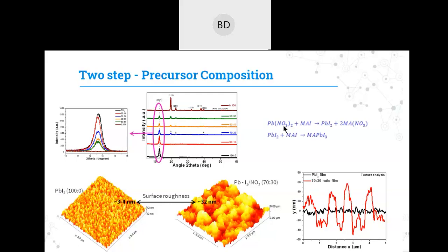What is this lead nitrate doing to change this kind of morphology? Generally, if you use lead nitrate with MAI, it doesn't directly convert into MAPbI3. It also goes through an intermediate phase change. First, if you use lead nitrate with MAI, it forms PbI2, and then that PbI2 with MAI forms the MAPbI3. So this is again an exchange reaction, which takes a little bit of time and gives sufficient time to have this kind of morphology.